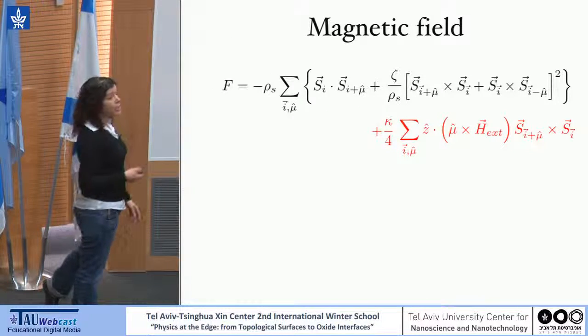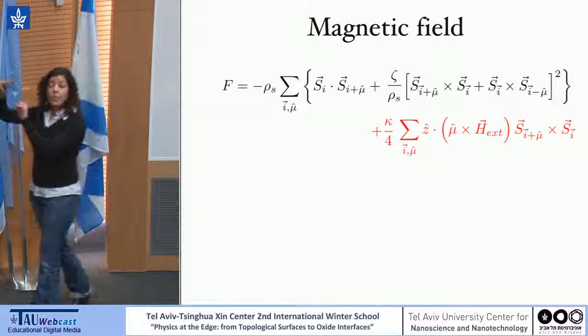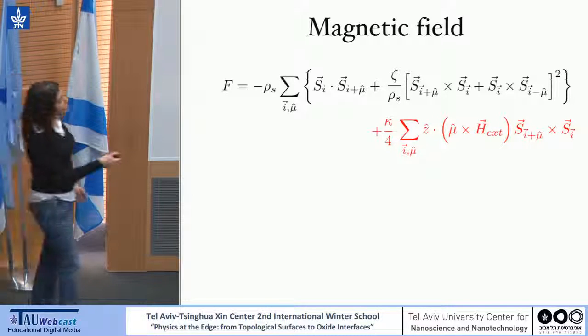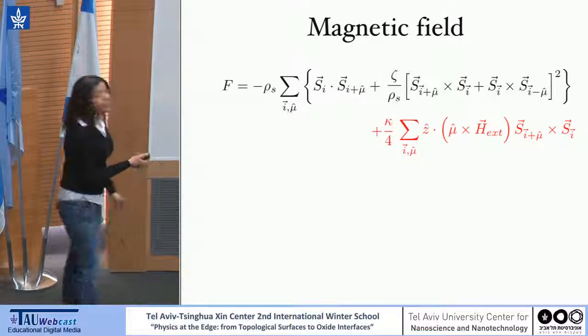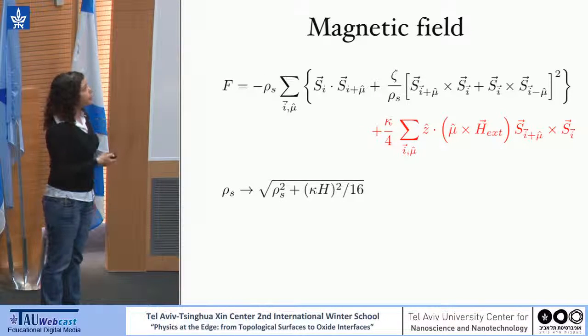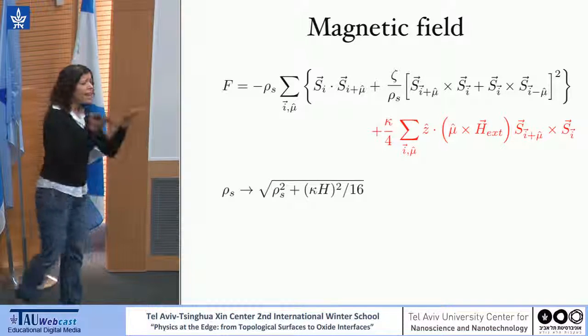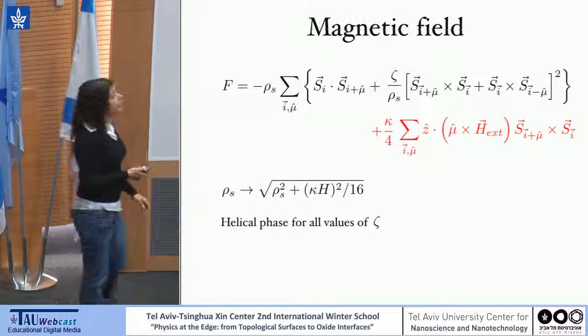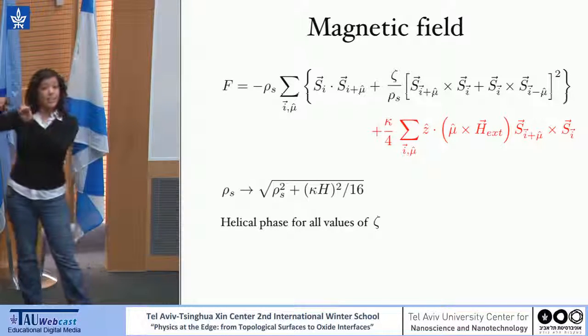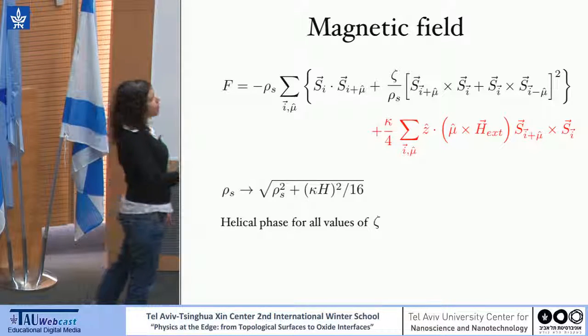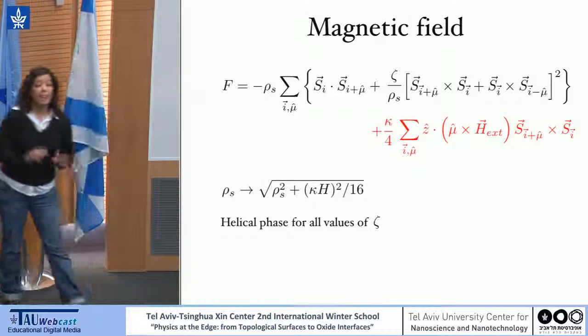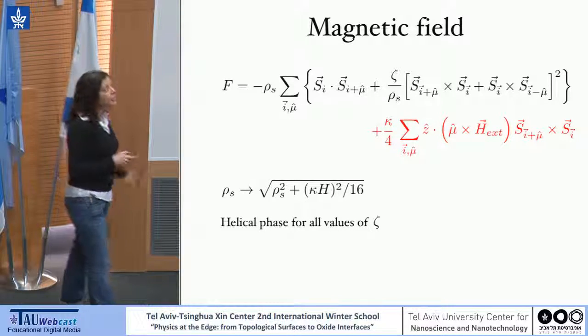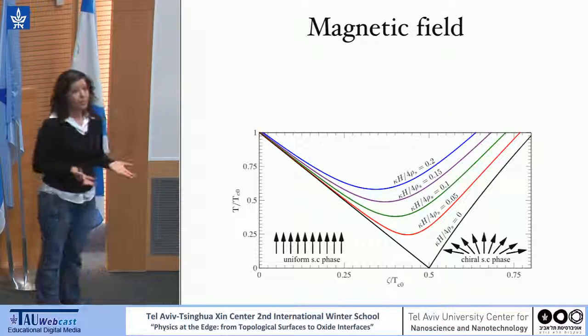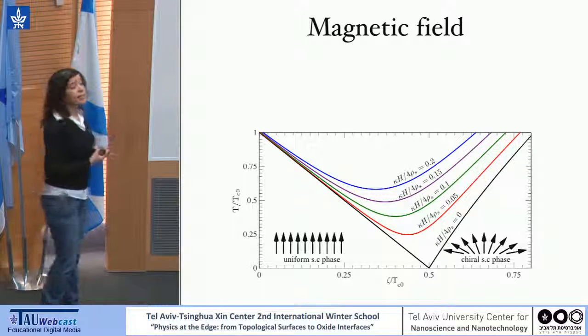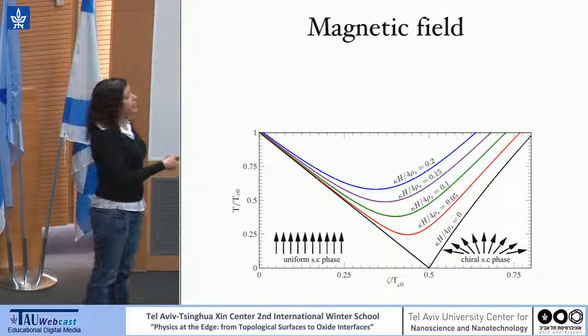Now, what happens when we apply a magnetic field in such a system? So, the additional magnetic field basically wants to help the system already rotate in a certain direction. So first, it chooses one direction for our spin to rotate, but also it helps it rotating, and therefore, it has two types of effects. First, it slightly increases the phase stiffness, and in addition, it gives us just a helical phase or some finite gradient, already for a very small zeta parameter, this kind of magnetic fluctuation term inducing chirality. And to just summarize this part, that will be our phase diagram in the presence of magnetic field.